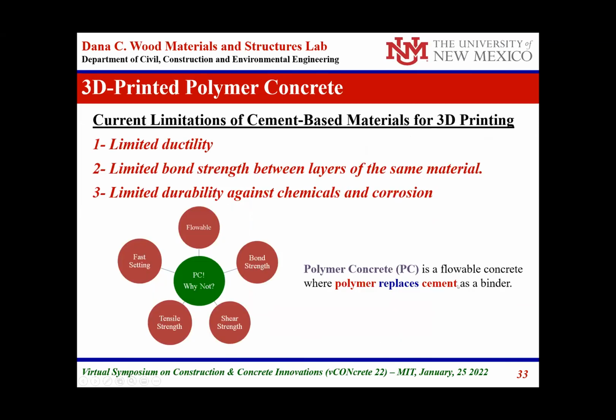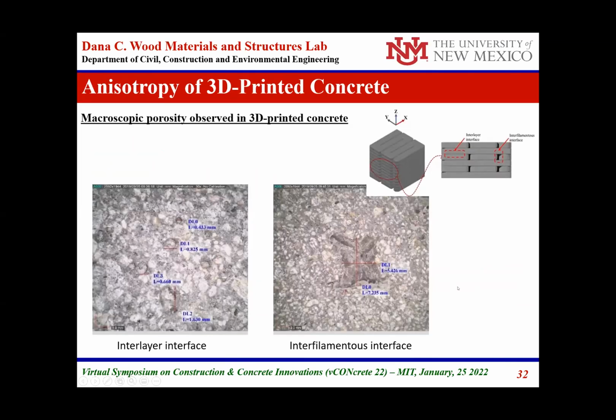So we conclude that in the case of 3D printed concrete, the increase in density and compressive strength in the X and Y direction is related to the fact that during printing, the nozzle pressure compacts the concrete, giving it a higher density and therefore a higher modulus of elasticity and higher strength.